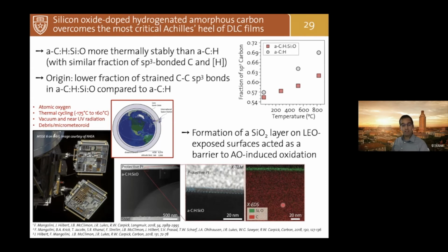And these experiments were also confirmed by an experiment we did in the lab, where we annealed the sample at very high temperature in a lab environment. And again, we observe this self-healing, self-protecting way of the material to create this oxygen diffusion barrier against oxidation of carbon.